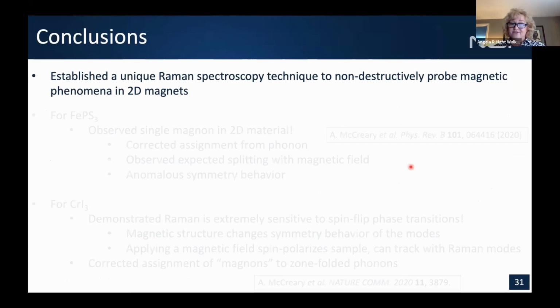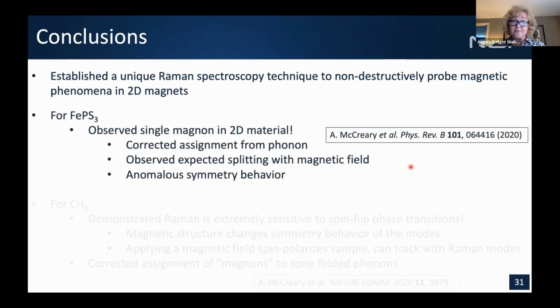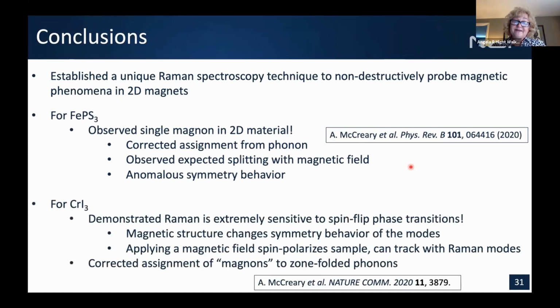So I hope that I'm able to convince you we finally have established our unique Raman capability to non-destructively probe phenomena in 2D magnets. And again, we're happy to discuss collaborations with people who think this technique might be of interest. In the iron PS3 case, we have corrected an assignment from a phonon to a magnon, and we also are beginning to understand this anomalous symmetry behavior for magnons. And then in the chromium case, it was exciting to see that Raman was very sensitive to the spin flip phase transition. The magnetic structure changes the symmetry of the modes, and that was quite exciting. And we corrected the assignment of a magnon back to a phonon.